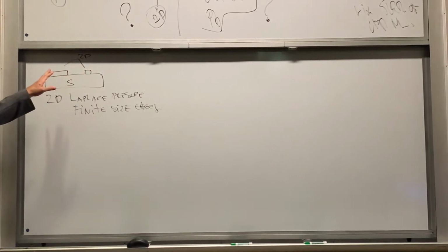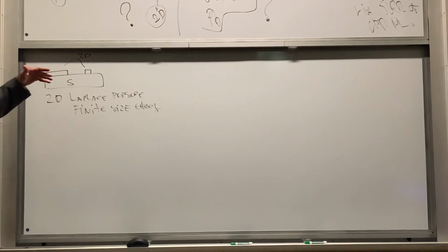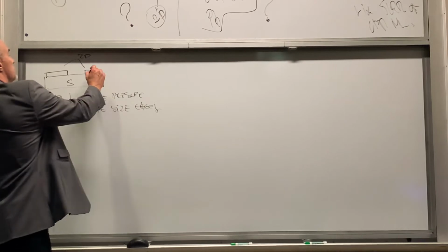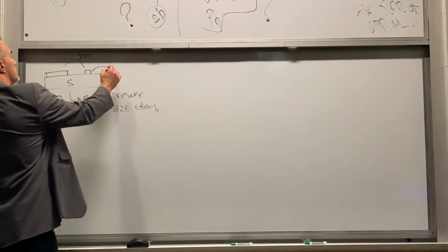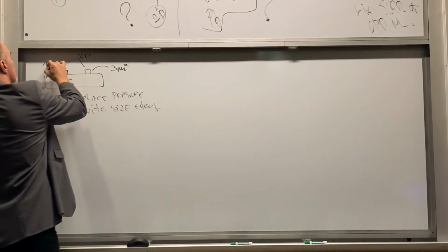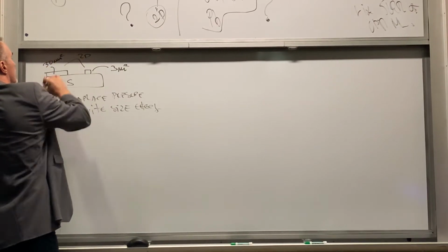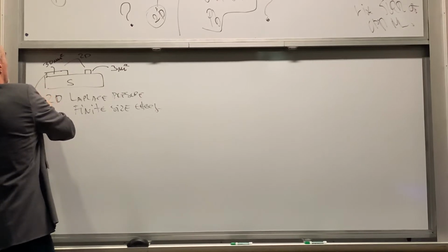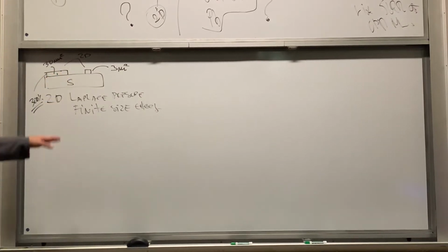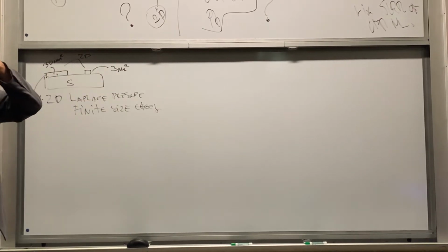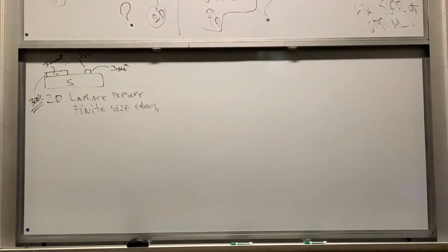The difference could be so huge that, for example, at certain conditions with small clusters, maybe 3 nanometers square, versus 30 nanometers square, you would probably need about 300% more area of this catalyst in order to get the same rate of the reaction.